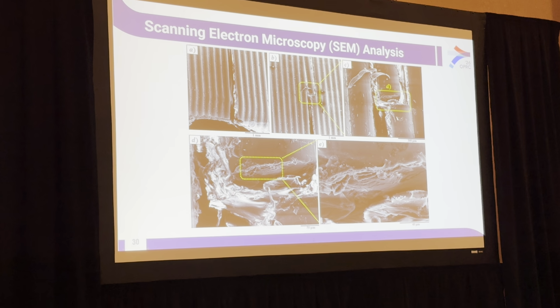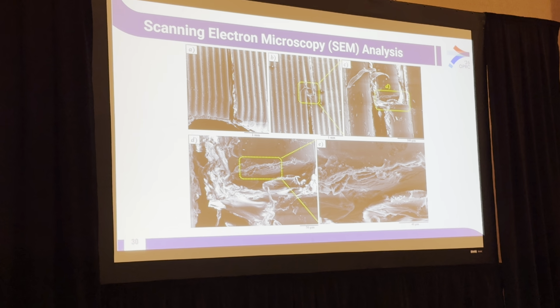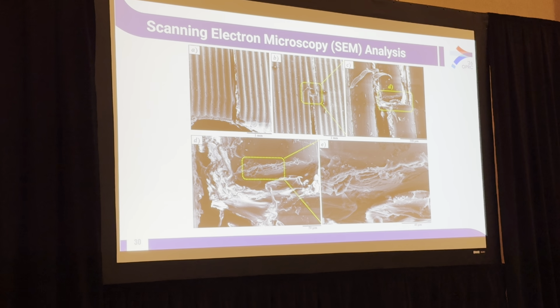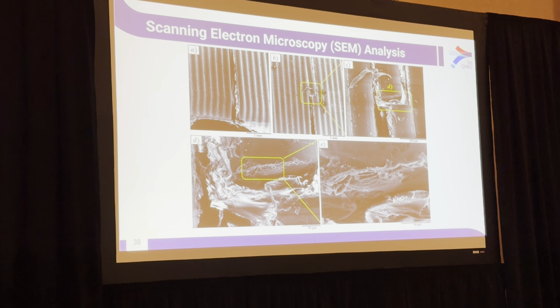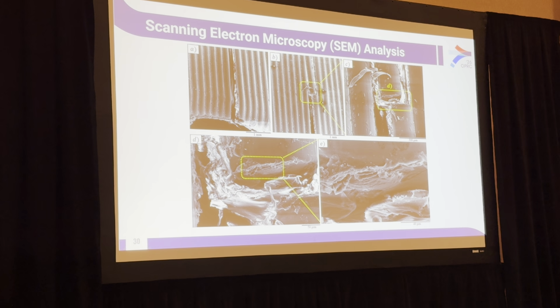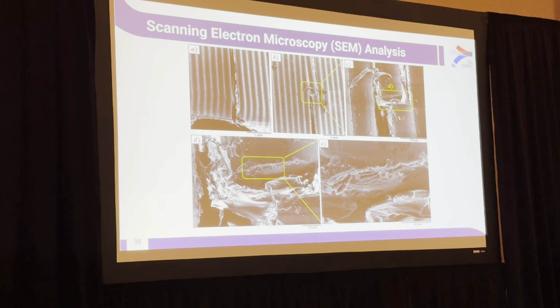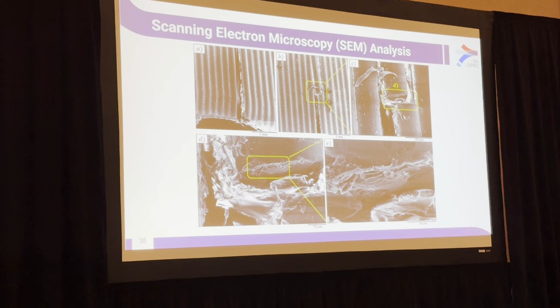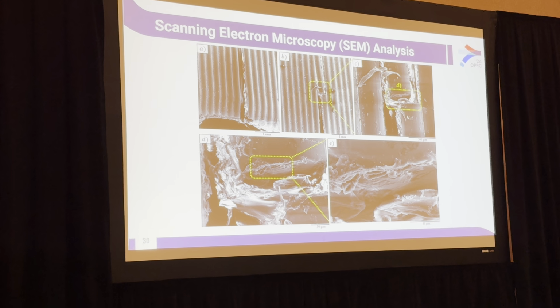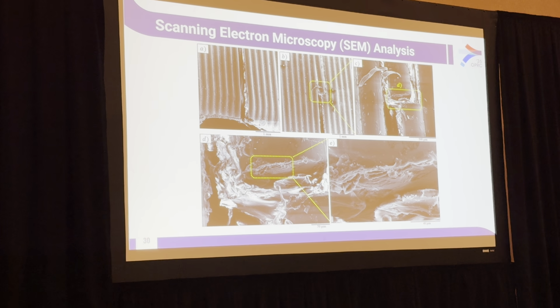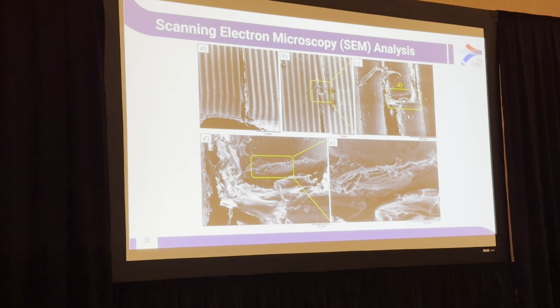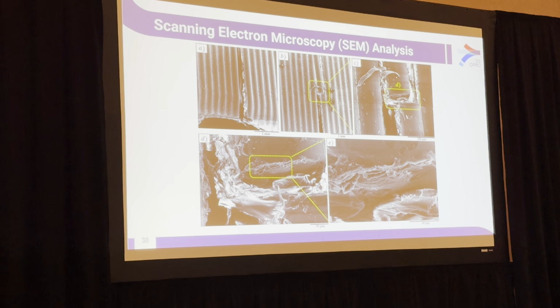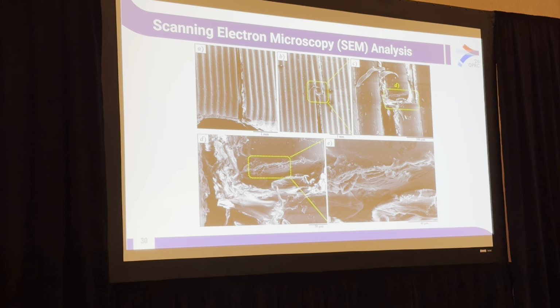So this might look a little crazy, but this was our further analysis. It's called scanning electron microscopy. And so this allowed us to look very closely at the fractures to try and understand the behavior of the failure. If you look here in image A, we actually see that the fracture starts by what's called layer delamination. And so the bond between those filament layers is actually being broken and starting the fracture. However, if you look at image B, we also see fracture across the filament strand itself, indicating the failure from that bulk material.